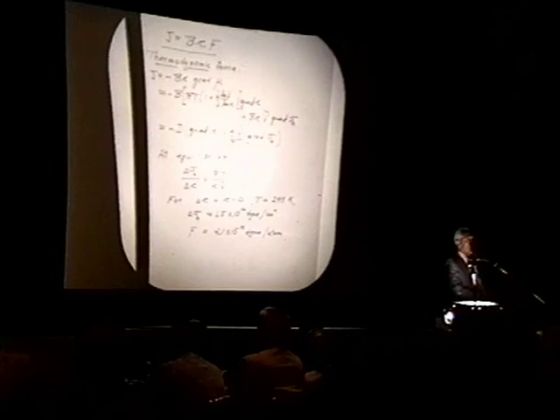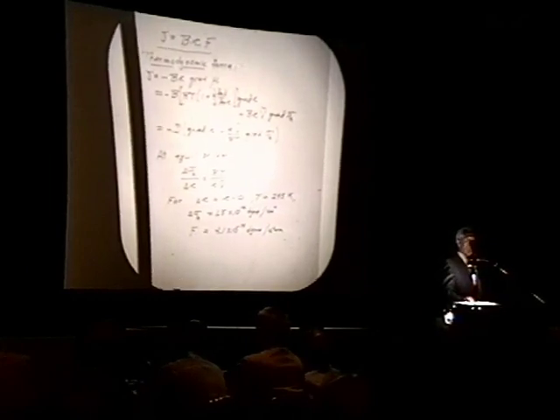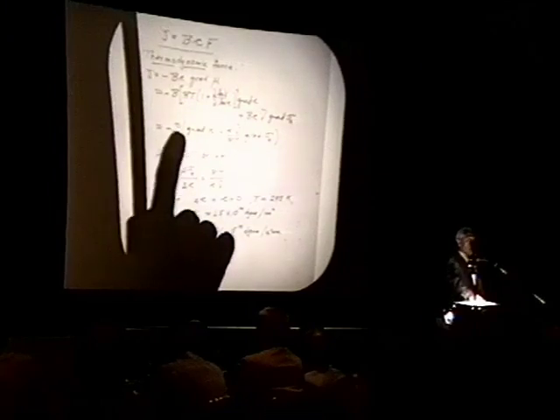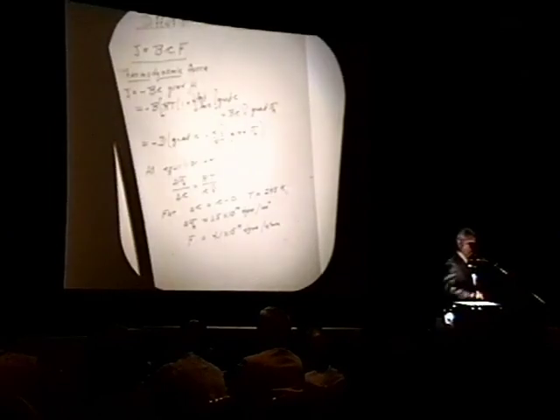In addition, one more thing I want to say: people have measured the ratio of diffusivity to concentration in highly concentrated hydrogen-metal solutions. And one finds that there are regions of the phase diagram where D goes essentially to 0. The reason for that is that this term goes essentially to 0 in the neighborhood of the critical temperature and composition. That's a well-known retardation effect. Mobility does not go to 0, but the overall diffusivity does. That's because of this thermodynamic term.